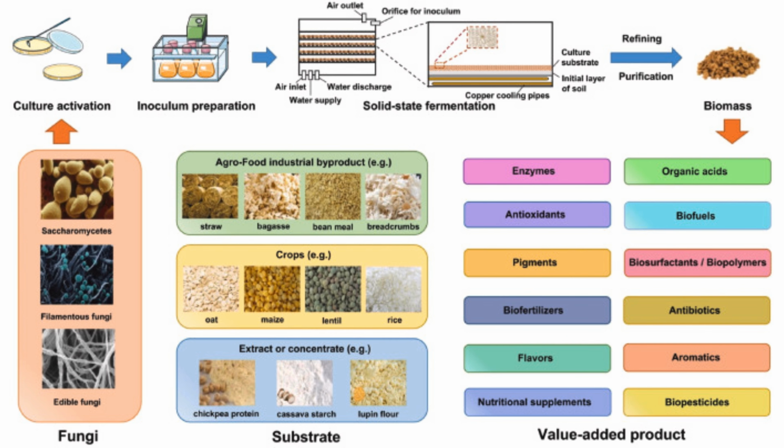Despite the low water activity of the SSF approach, the growth substrates usually possess adequate moisture to support microbial metabolism, and this could be in the range of the maximum water-holding capacity of the solid substrate. It has been observed that the purpose of producing pure mycelial mats, which is the starting material for fungal leather substitutes, is better served under SSF. This is important because fungi typically require direct contact with their growth substrate. Thus, they tend to be intimately tethered to their nutrient source. However, the production of fungal leather substitutes demands the use of non-woven fungal mycelial mats, which can only be harvested from the top surface of SSF or LSSF trays.